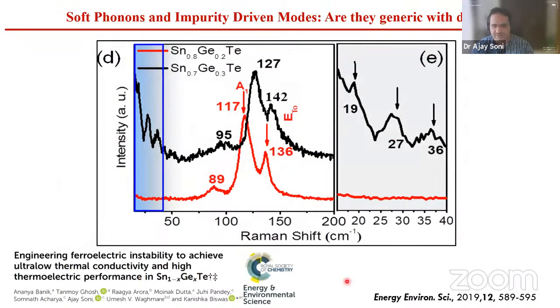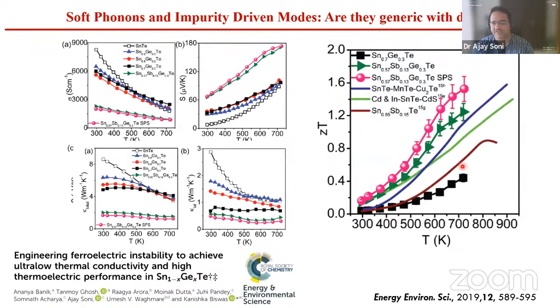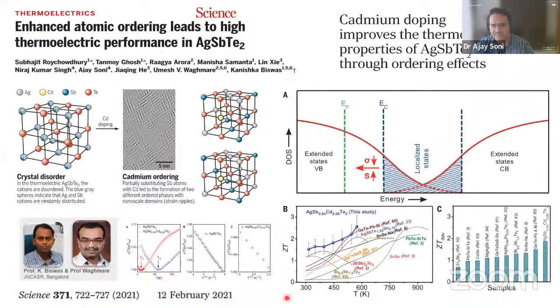This is the sample we got from our collaborator Dr. Kanishka Biswas and Professor Waghmare in JNCASR. And these modes are actually available, I mean, they come if you dope it with anything in SnTe, like germanium, Mn, or anything. So this depends on the doping level, and that actually creates a poor thermal conductivity in these materials. And these materials have a very high figure of merit. It was reported in Energy & Environmental Science.